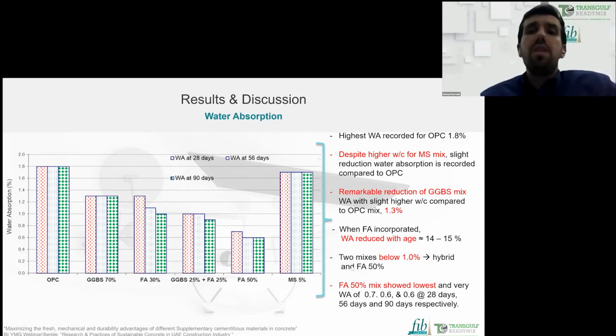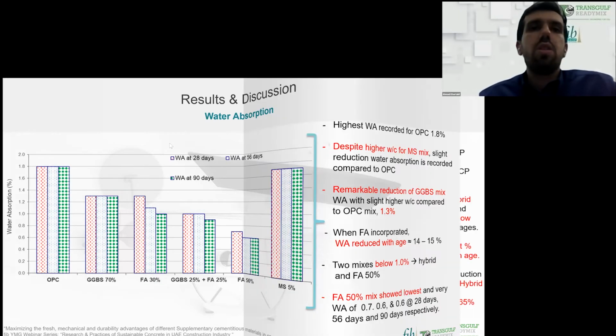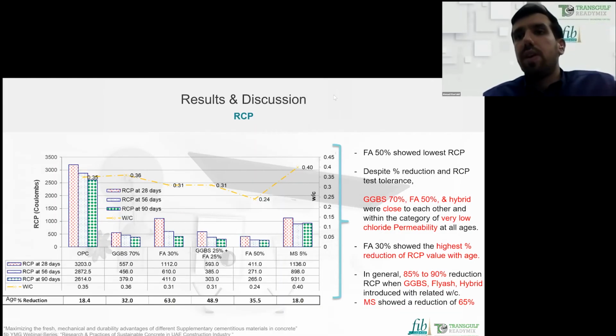And the hybrid mix achieved around 1%. So we're talking about very low water absorption when we are incorporating the fly ash to reduce the water demand in the concrete mix, while maintaining, of course, a good workability with the fly ash due to its spherical particles. And the fly ash used here is actually a Class F fly ash.